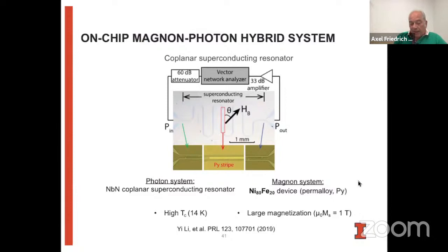And then after having a better superconductor than what most people use, we used a worse magnet than what most people use. So we used a permalloy device instead of yttrium iron garnet. One of the reasons simply is that the permalloy was very easy to integrate with this superconducting resonator. And the other reason is that making really good YIG that is still really good YIG at low temperatures is a really tricky business. And so we did something easy here. The advantage is that we have a much larger magnetization than we would have with yttrium iron garnet. And so that will also help us in terms of getting into the strong coupling regime.